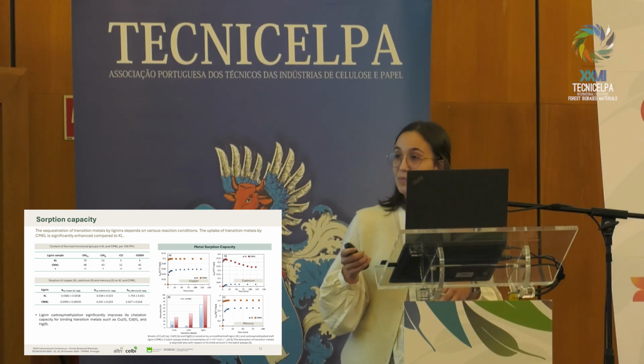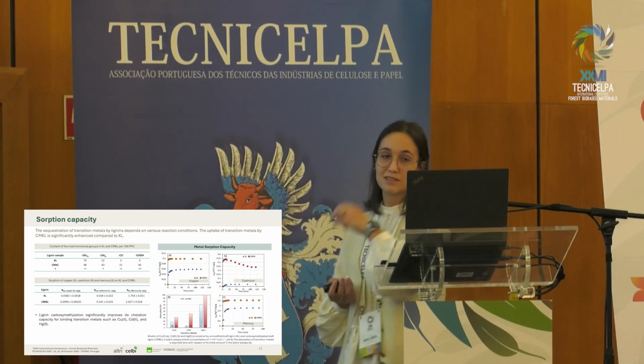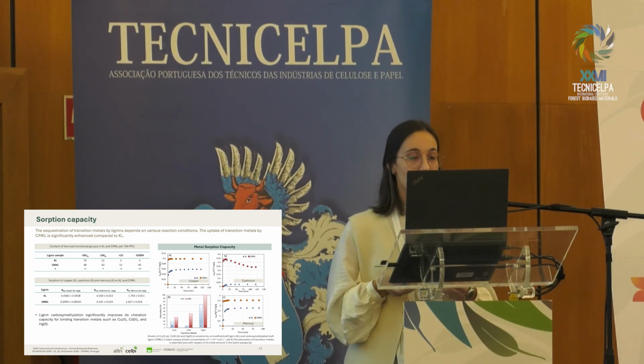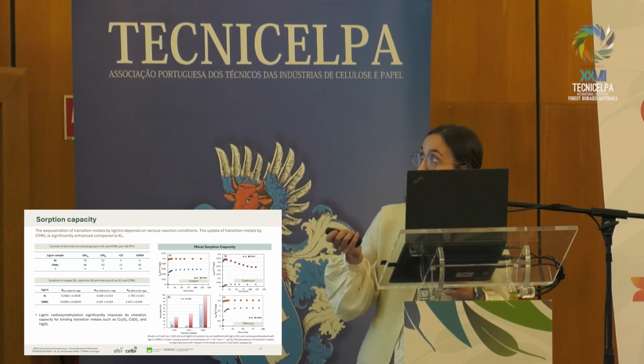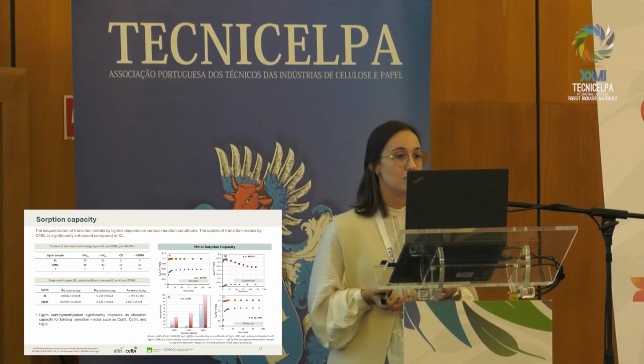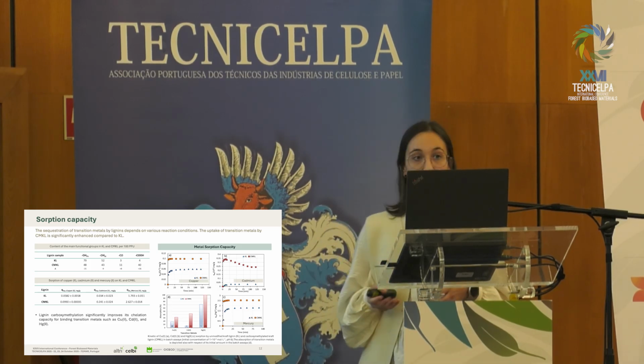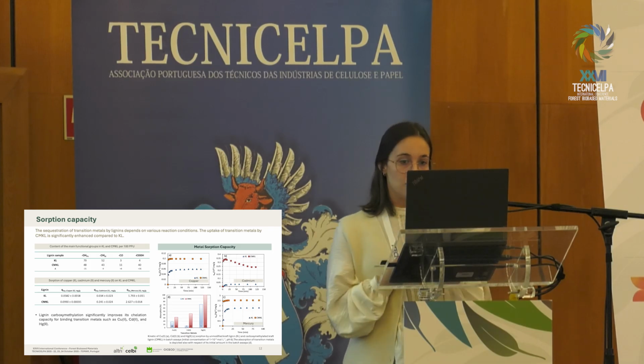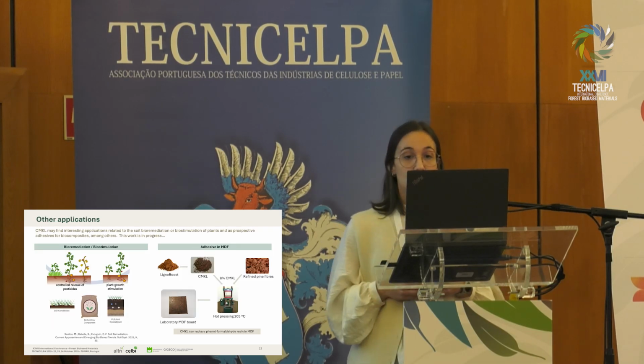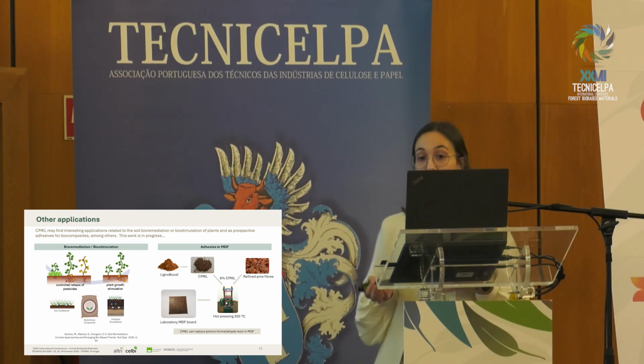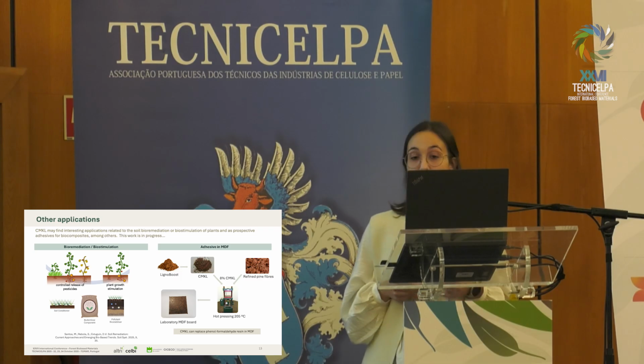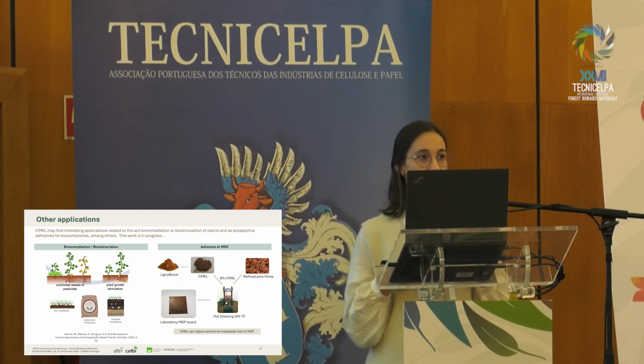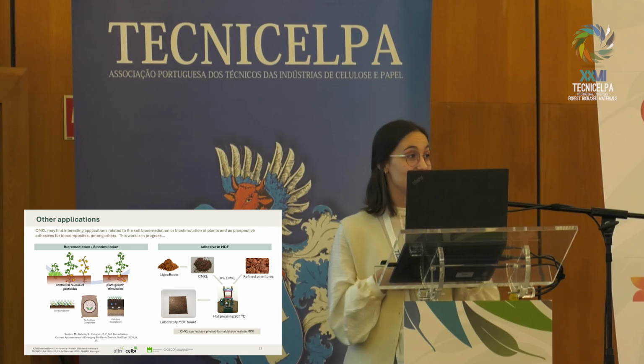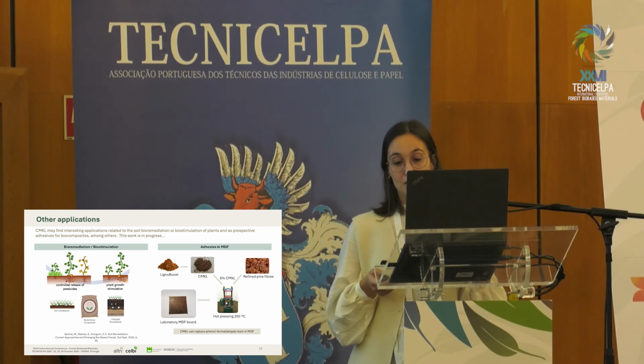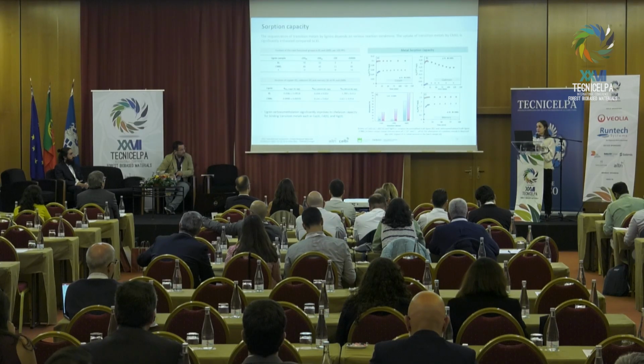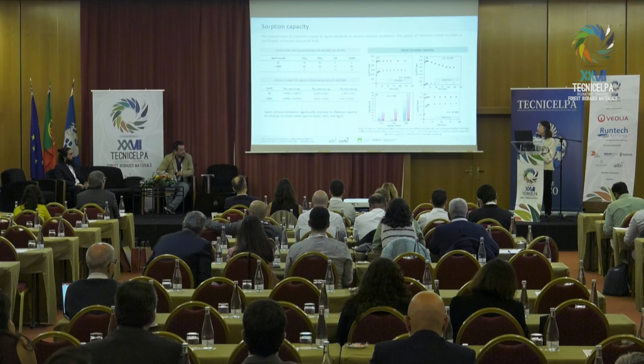So, during this presentation, we have talked about the introduction of these carboxymethyl groups into the kraft lignin, and these carbonyl or carboxyl groups in this modified lignin are strongly related to its chelation capacity. To test these abilities, tests were conducted in batch mode using low concentrations of copper, cadmium, and mercury solutions, in the order of 10 to the power of -5 molar, which is really low. We use such low concentrations because they correspond to the minimum emission values.